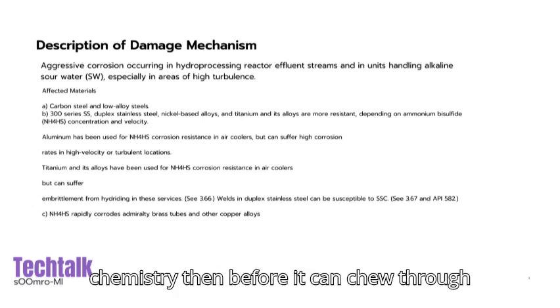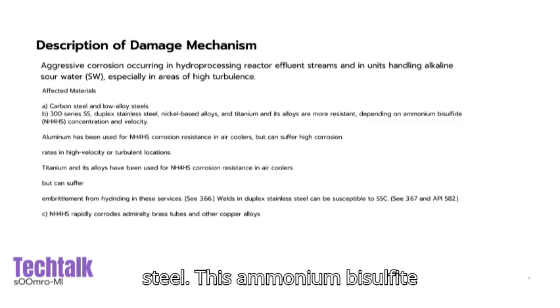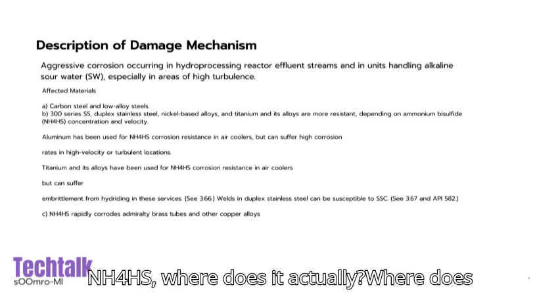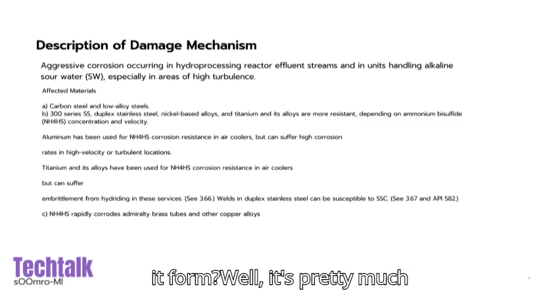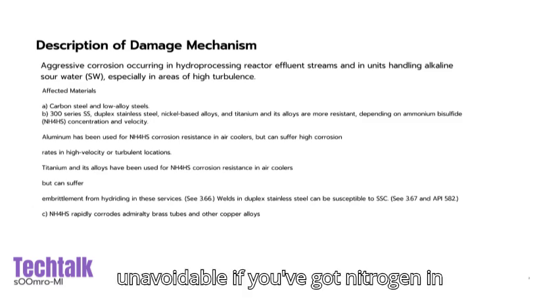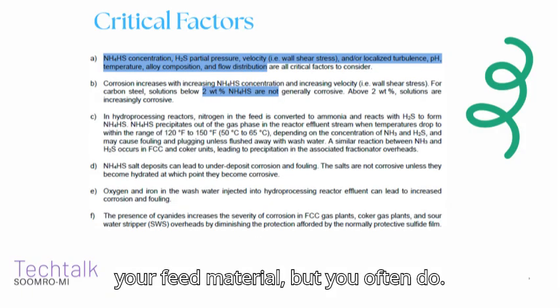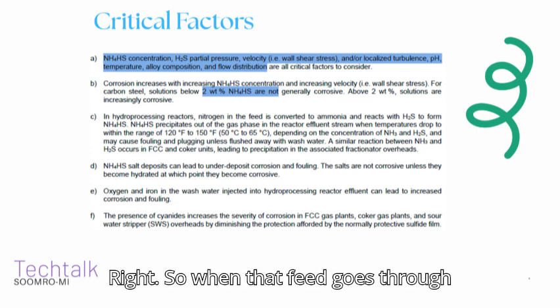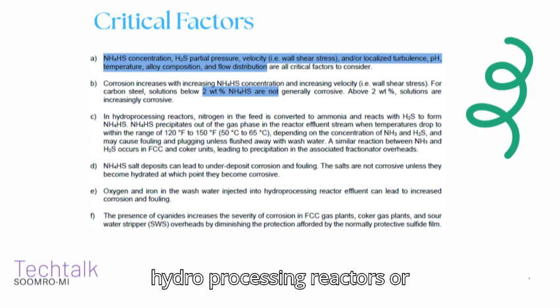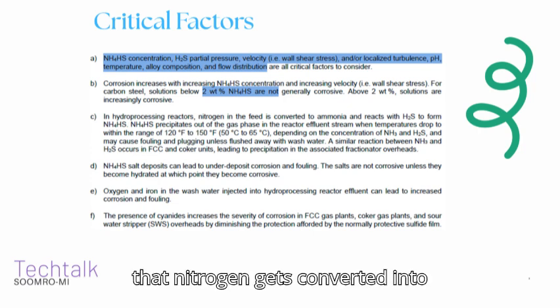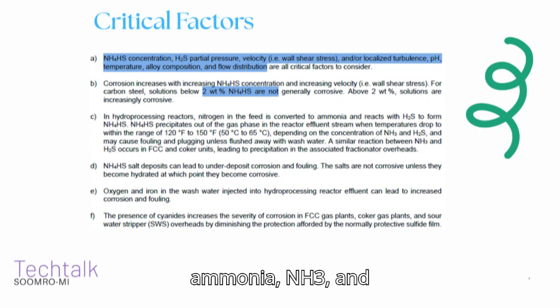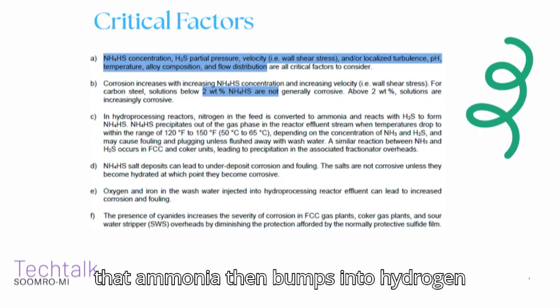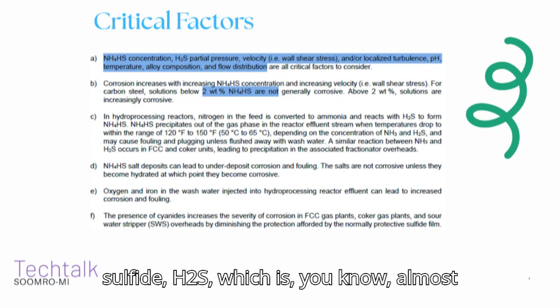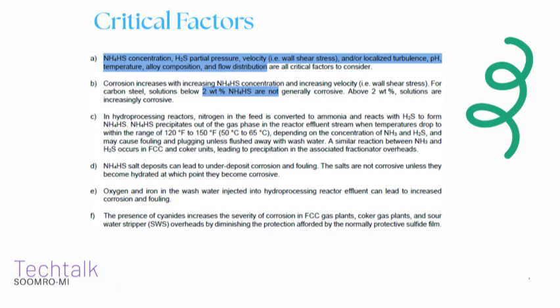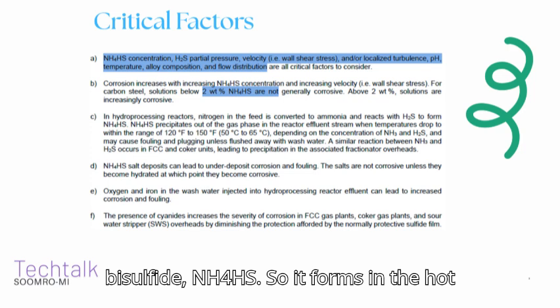Okay, let's unpack the chemistry then. Before it can chew through steel, this ammonium bisulfide, NH4HS, where does it form? Well, it's pretty much unavoidable if you've got nitrogen in your feed material. Which you often do. Right. So when that feed goes through hydroprocessing reactors or FCC units, cokers, that nitrogen gets converted into ammonia, NH3. Okay. And that ammonia then bumps into hydrogen sulfide, H2S, which is almost always present in these sour streams. Sure. They react, and boom, you get ammonium bisulfide, NH4HS.